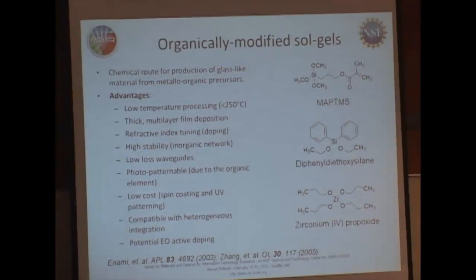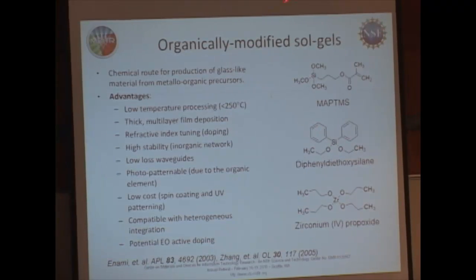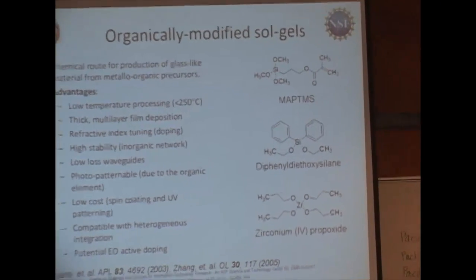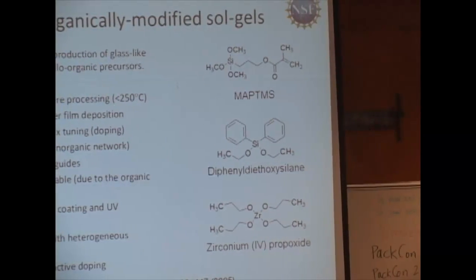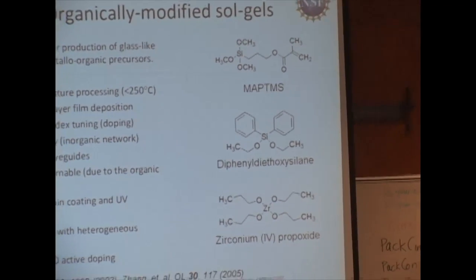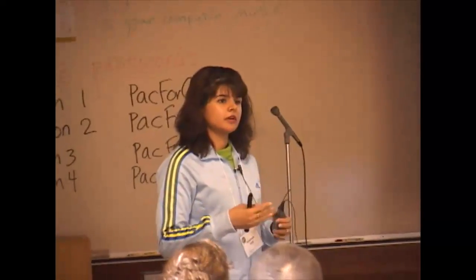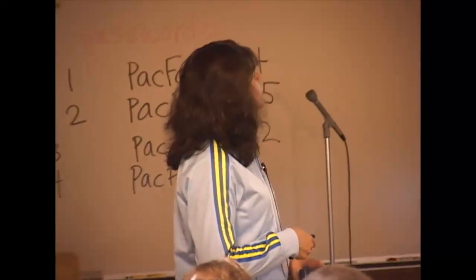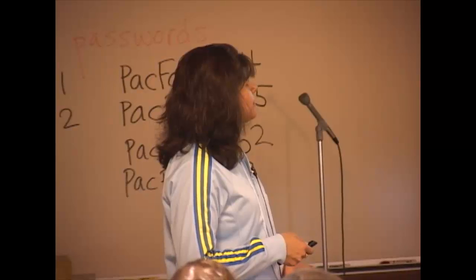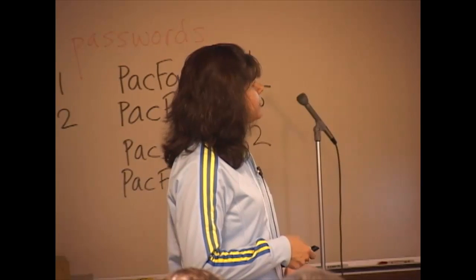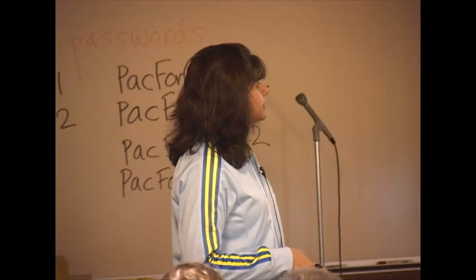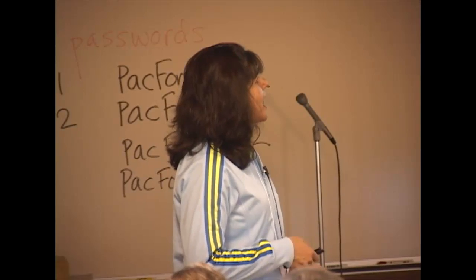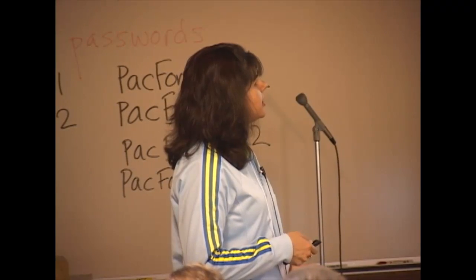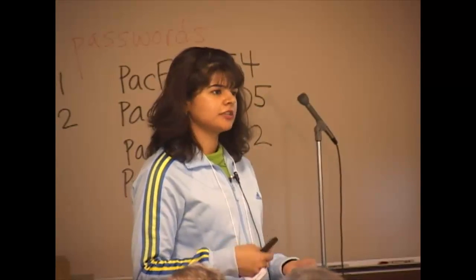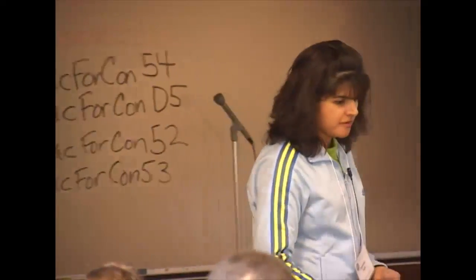In addition to EO polymers, we use modified sol gels as our cladding layers. And so sol gels have a number of advantages, including their low temperature, their refractive index tuning, just by mixing different amounts of starting materials. They're photopatternable. And so we use MAPTMS, diphenyldiethoxysilane, and then zirconium propoxide. And if you add different amounts of the starting materials, you can tune the refractive index so you can guide the light in a certain direction.